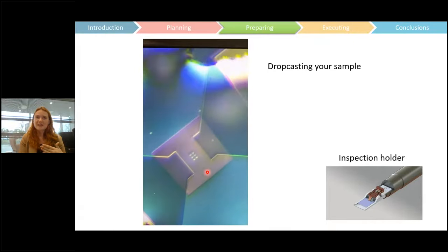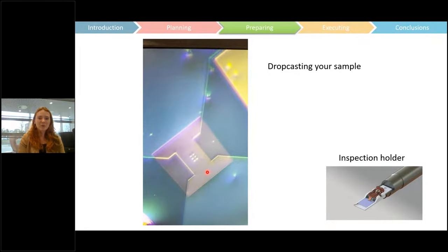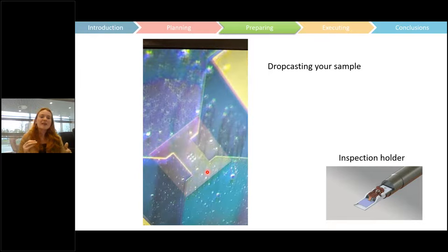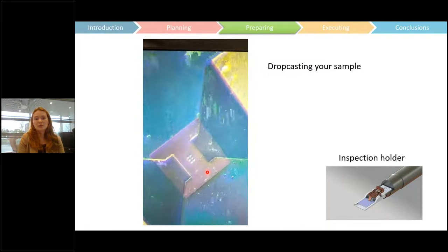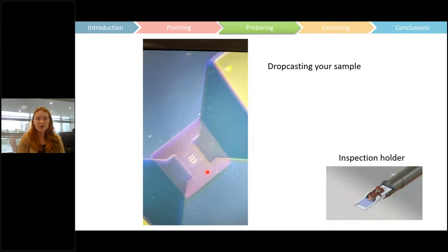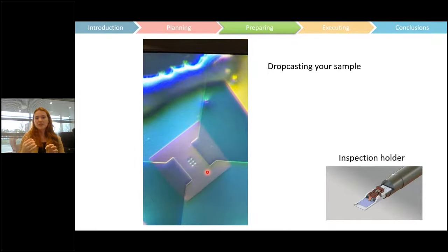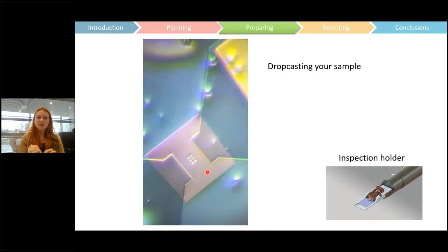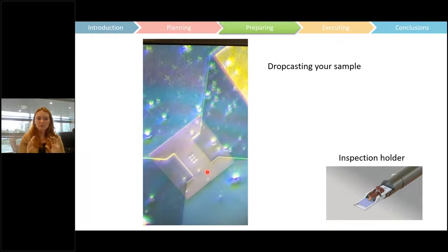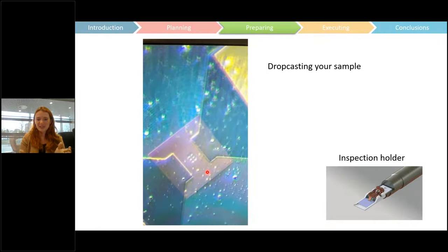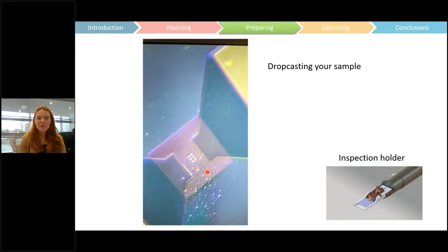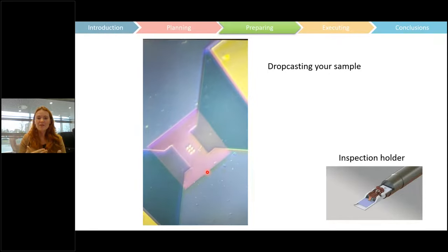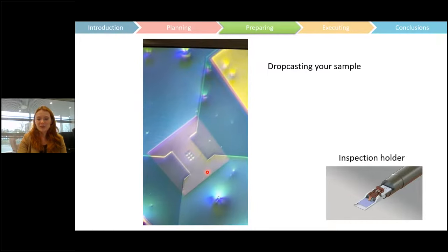So you just increase your risk of leaks as opposed to getting more sample. If you have very, very sharp samples, things like magnesia, ceria, titania, it is extra important that you get a really small fraction of particles. You can get little filters that you use a syringe to press through that will sort out so you don't have too many large particles in your sample. But it is really, really important to try and practice this part and get the right sample dispersion on your chip.